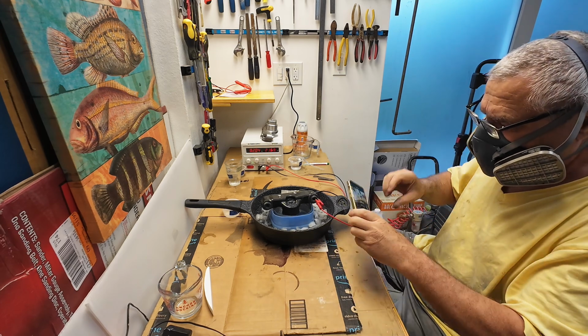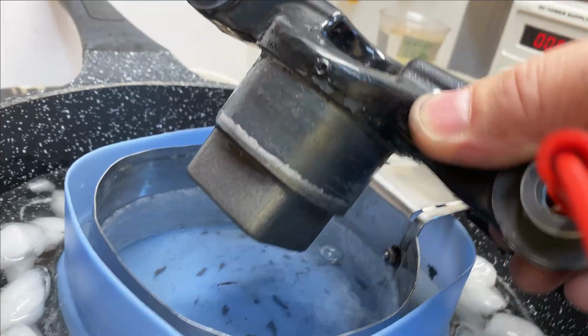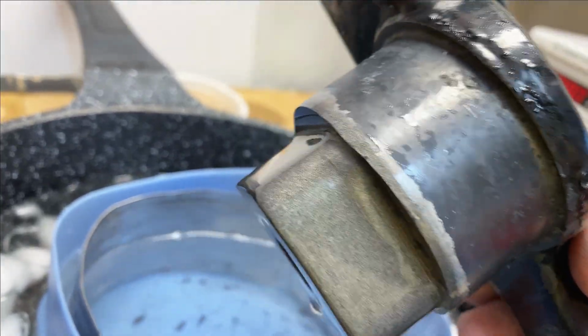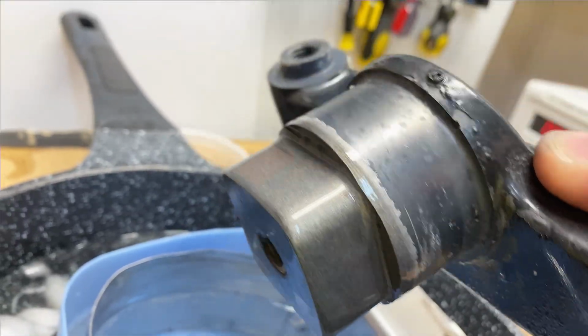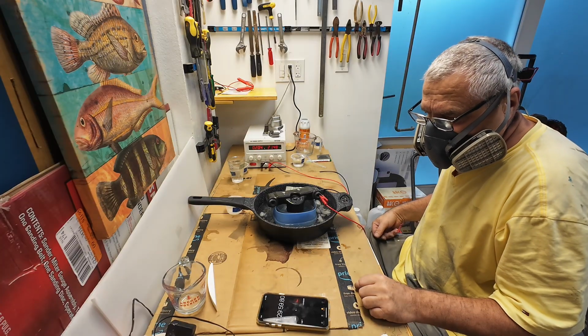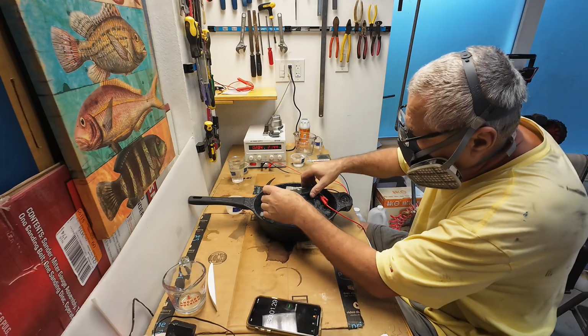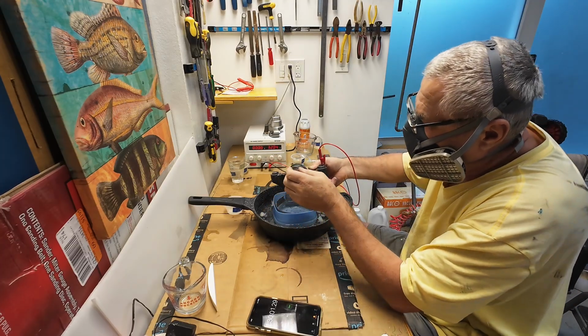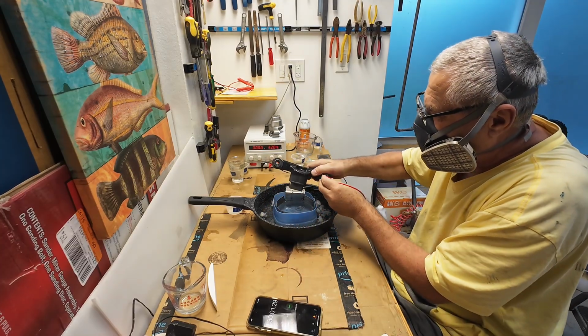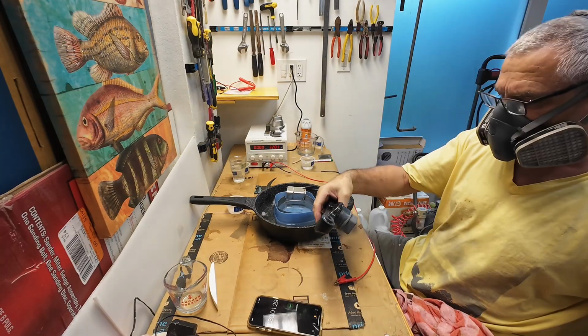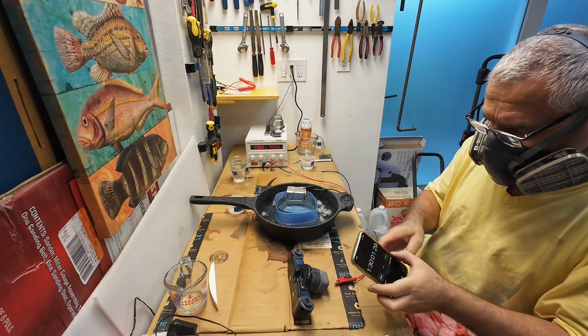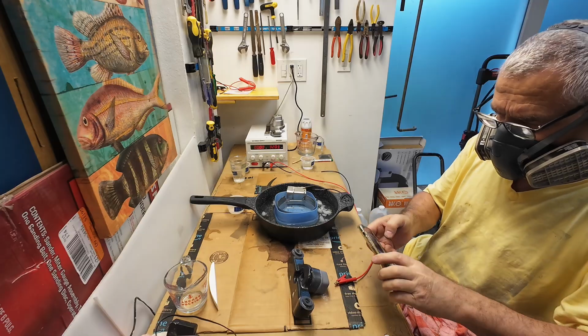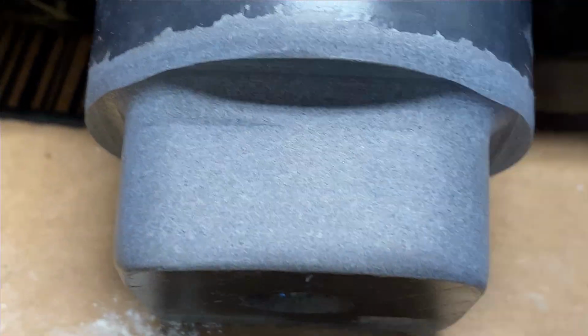More than an hour has passed, and the result is excellent. The oxide film is uniform and feels quite thick to the touch. An hour and a half has passed. I think that will be enough. The result exceeds all my expectations. I ended up with a perfect and very hard surface.